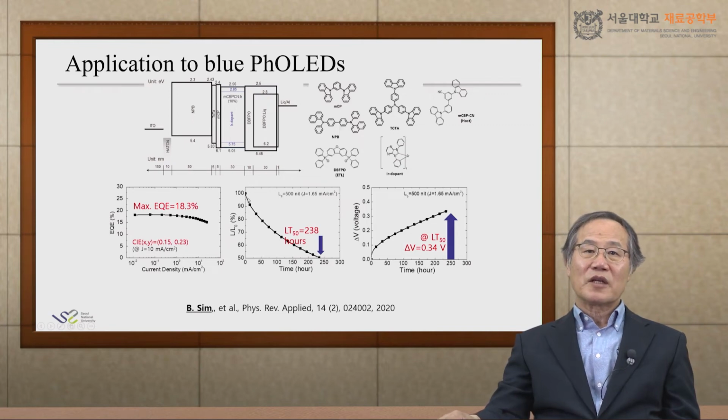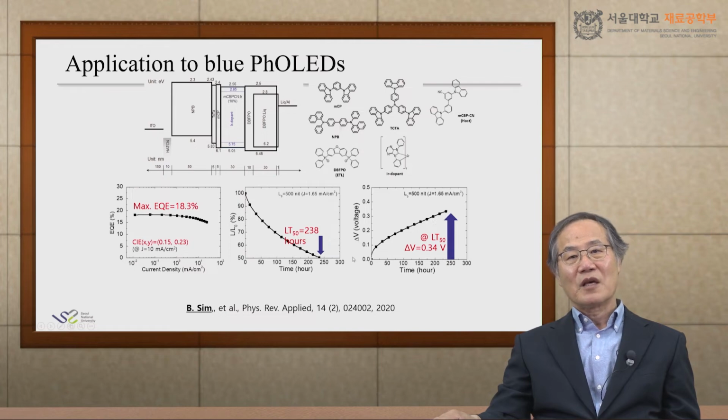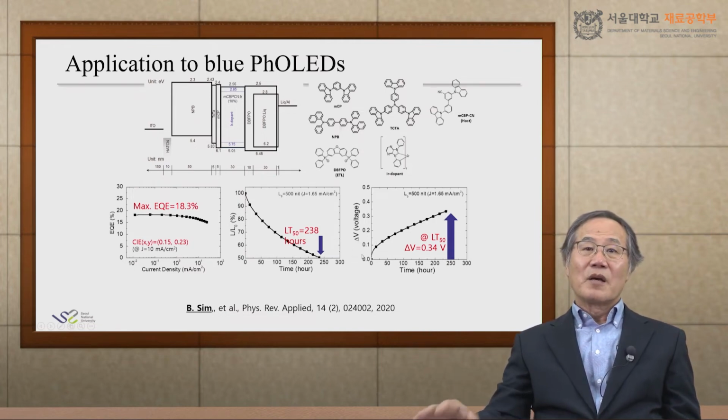So this is the degradation, usually observed. Originally, at constant driving, it is 100%, but it is reduced gradually with time. Here in this case, after 238 hours of operation, the light emission was reduced by 50%. At the same time, driving voltage increases with that. So we need to quantitatively analyze that.